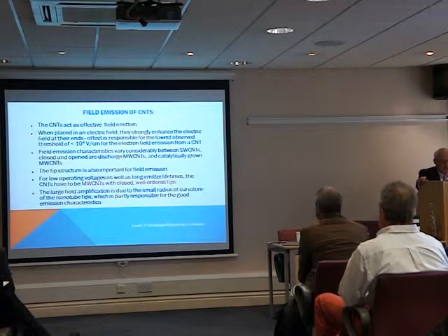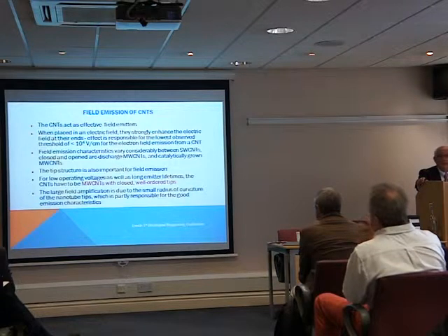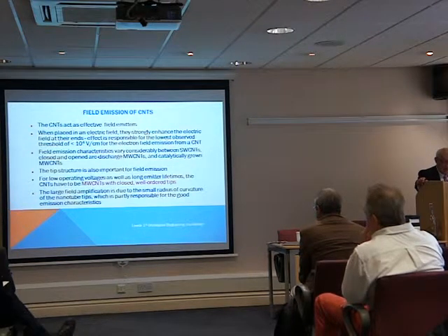When placed in an electric field, they strongly enhance the electric fields at their ends. And this effect is responsible for the observed threshold I've shown here of less than 10 to the 4 volts per centimeter for the electric field emission from a carbon nanotube.